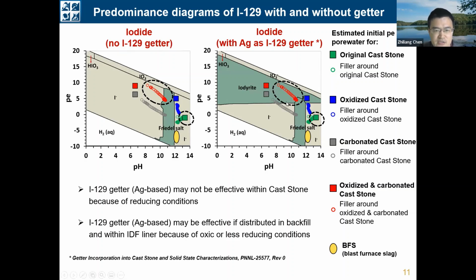But if we take a look at these round open dots, they are in the region of insoluble iodine for the system with the getter. So that means the getter may be effective if it's distributed in the backfill or within the IDF liner because of the oxic or less reducing conditions there. And also, if we take a look at this red square dot, it's also in the region of insoluble iodine. And this is the redox state for the oxidized and carbonated Cast Stone. So that means the oxidation and carbonation is actually beneficial for the stabilization of the iodine for the system with the getter.